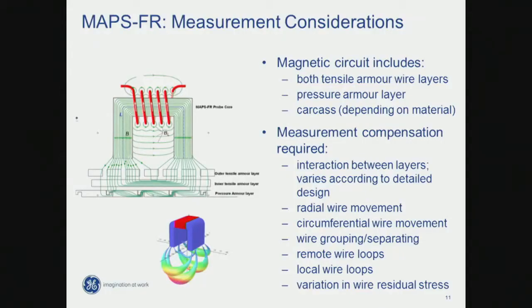So flexible pipe. Now, measuring on a piece of flat steel like this, a semi-infinite plate, that's easy. For flexible pipe, it isn't easy. In fact, it isn't being round is not helpful, but the bigger problem is, of course, it's an unbonded structure with lots of steel elements within it. And the coupling, our probe is essentially a C-core, and there are sensors around the C-core. The flux couples with all of the layers within the structure. And so we need to have an understanding of how the magnetic flux interacts with all those layers to be able to make sense of it.